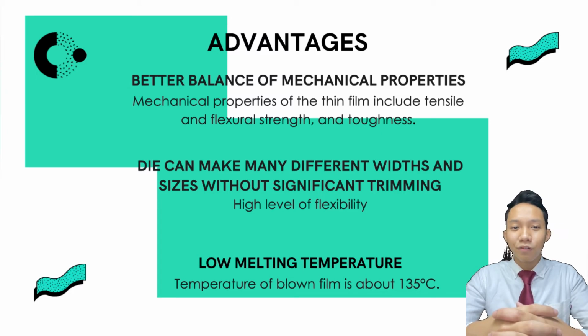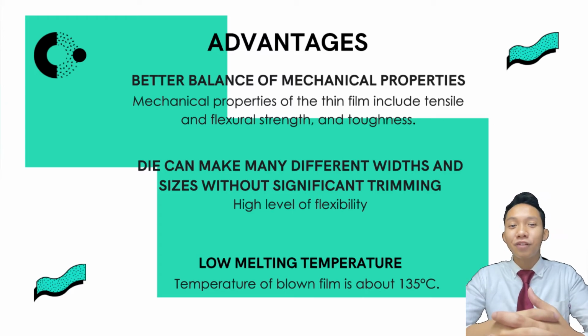Furthermore, blown films also require lower melting temperatures than cast extrusion. Measured at the die opening, the temperature of the cast film extrusion is about 220 degrees Celsius, whereas the temperature of the blown film is about 135 degrees Celsius. Furthermore, the cost of the equipment is approximately 50% of the cast line.